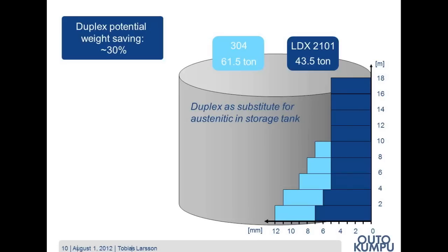While in the duplex case, you can start with a wall thickness that goes from 7 millimeters, 6 millimeters, and then 5 millimeters for the upper part of the tank. And the reason why you cannot save anything in the upper part is because of the design rules of stability and such. So in this case, just by substituting the austenitic grade for a duplex grade, you will have a weight saving of approximately 30%.